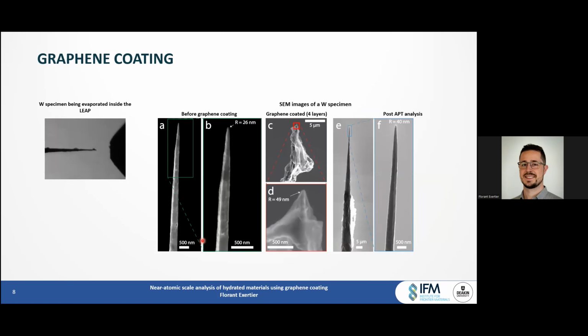So here we can see a tip before graphene coating right here, and the same tip after it was coated 4 times with graphene, and then again the same tip imaged after atom probe analysis. So firstly, we can see that the graphene drapes the specimen like bed sheets and takes quite some space compared to the initial volume, and also as shown here on the atom probe monitor screen. However, during the evaporation, we can see that the graphene protrusions change or get removed throughout the acquisition.